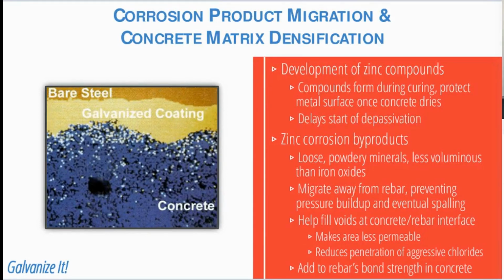Next, hot dip galvanized rebar offers further protection because the zinc corrosion products actually migrate towards the concrete in a different way than iron oxides do for the uncoated rebar. Zinc corrosion products are actually less voluminous than iron oxides or steel corrosion products, and they disperse away and actually migrate into the concrete and even fill the pores of the concrete in the nearby area.